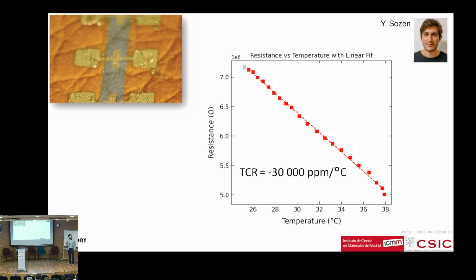We also fabricated temperature sensors, thermistors, because one of the advantages of these devices is that they are a semiconductor material, an N-type with the Fermi level very close to the conduction band. It's almost N-type doped from the intrinsic properties. So a little change in temperature is enough to change the population of charge carriers just by thermal activation. And because of the nature of interconnected flakes in these films, a little change in temperature also changes, because of thermal expansion, the coupling between the layers by sliding. These two things together make the resistance of these devices extremely sensitive to temperatures within room temperature.